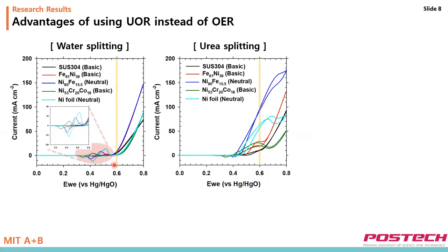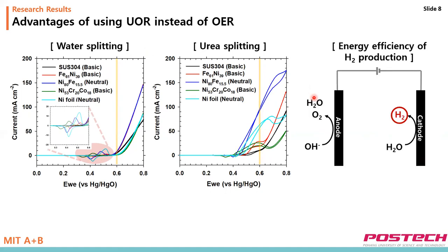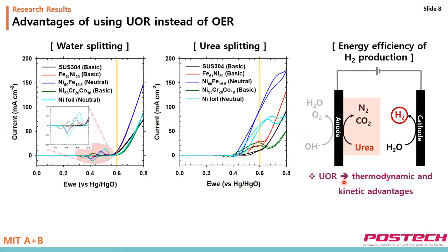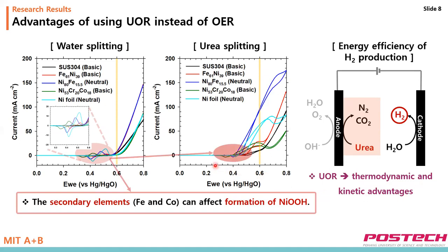At specific applied voltage, obtained current densities show much higher value in urea splitting than water splitting. This means that the use of urea electrolysis can enable more hydrogen production because UOR has a thermodynamic and kinetic advantage. As shown in the graph, the secondary elements can affect the nickel oxyhydroxide formation.